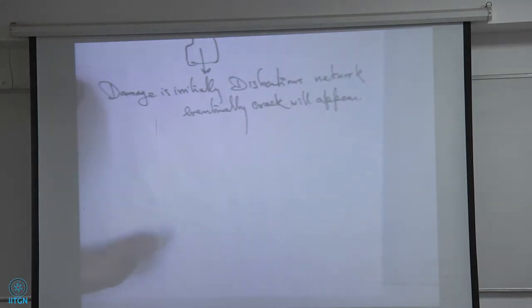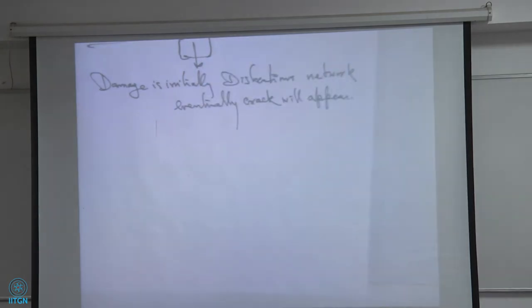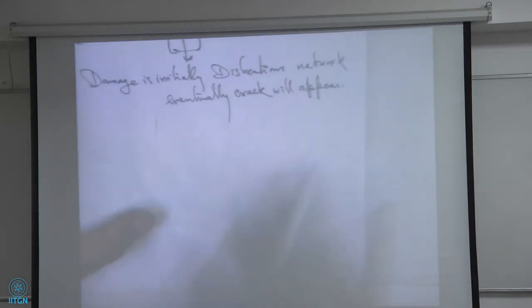So there are dislocation networks here. You're hitting ultrasonic energy into this, not with a transducer, but with an ultrasonic horn. It's emitting very powerful waves. And here it's not touching the sample, so a lot of it is going in air actually. So you're going to lose some of it, maybe 25% is gone. So you're only using 3/4 of the energy, okay? And I can look up the details actually.